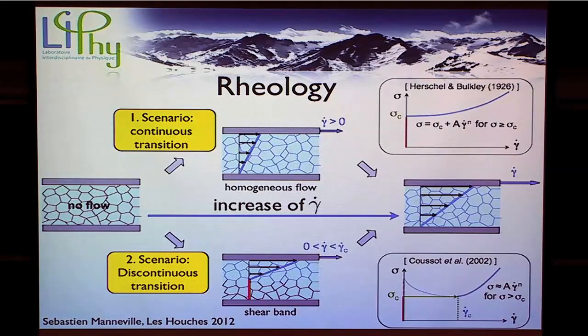And this is associated with a phenomenological law, the Herschel-Bulkley law, which is given here with a finite yield stress and some power law behavior in the shear rate. But there's also a second scenario possible, which is a discontinuous transition, where if you increase the shear rate, the medium in the steady state is not responding homogeneously, but there are shear bands forming up to a critical value of the shear rate.